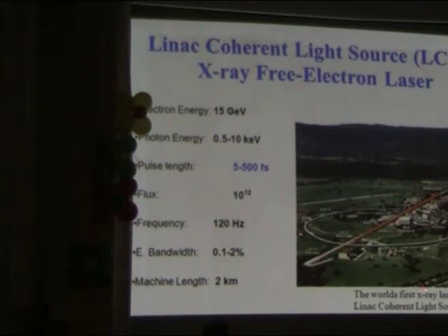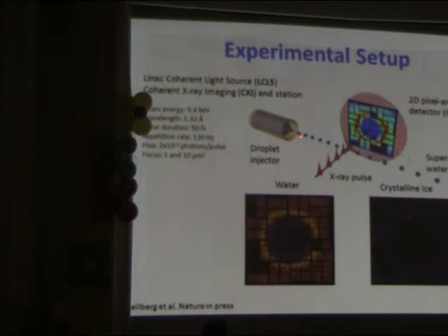What we have used is the X-ray laser at SLAC at Stanford. This is the first X-ray laser. It's a free electron X-ray laser, and it gives fully coherent pulses of X-rays, very, very intense, and very, very short. So you can do down to 5 femtoseconds. What we do experimentally is to generate small micron-sized droplets that fall in vacuum. As they fall in vacuum, they cool through evaporation, and they cool very rapidly. They are hit by one of these pulses, and from individual droplets, we get a full diffraction pattern. We can distinguish if we have liquid water, then we have the water rings, or if we have crystals in the droplet, we get Bragg peaks.